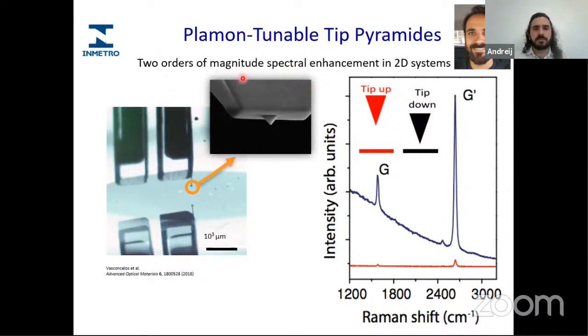This is a picture of it. So we have a truncated pyramid, and on top of it, we have a smaller pyramid here. And here's a picture of this special tip coupled to a tuning fork. To show you how powerful this nano antenna is, I show here the Raman spectra of graphene. In red is the standard spectra of graphene, and in blue is the spectra when the tip is down, so when the tip is in interaction with it. And we have these ultra large enhancements of the order of 100. And just for comparison, the standard commercial tips give about 2 times enhancement.